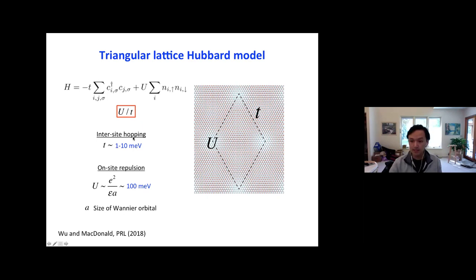So in some sense, the TMD hetero bilayer is actually the simplest moiré system, because it's just described by a single orbital Hubbard model. So it looks something like this. You can think of it that each moiré site is an energy trap for electrons. An electron can tunnel between sites with an amplitude t, and then with an on-site repulsion U. And typical t in this system is about 1 to 10 meV. And the U, you can estimate from the size of the Wannier orbital in the system, it's about 100 meV. So U is typically quite a bit bigger compared to t. That's our expectation.